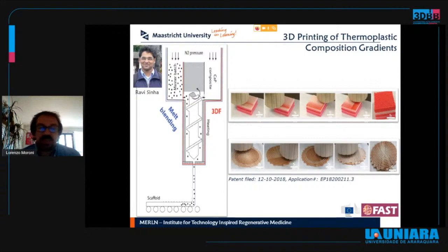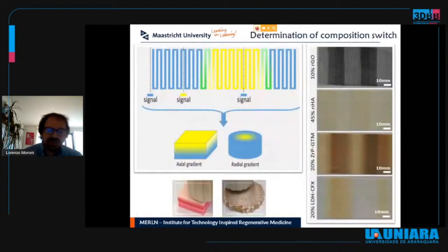And so, with that idea in mind, we also developed more recently a new additive manufacturing technique where essentially we combine blending with classical extrusion-based deposition. So in this case, we can change the composition of two materials while we print in the same layer, and we are therefore not limited by changing the material composition every certain amount of layers.